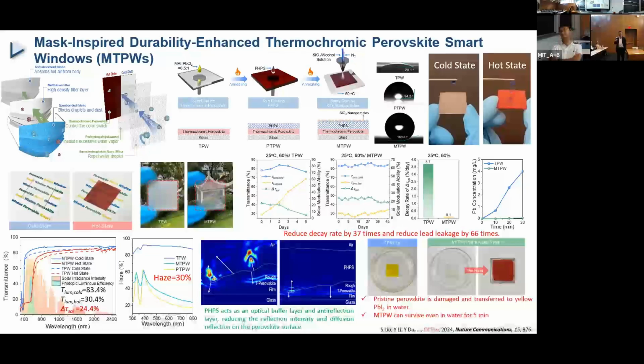This is the previous common perovskite window with a high haze, so that we cannot see the object behind the window. Because the PHPS layer acts as an optical buffer layer and anti-reflection layer, these 2 layers can reduce the reflection intensity and the diffusion. In this way, the haze will be dramatically reduced from 90% to like 30%, so we can see the object clearly. So how about the durability and lifespan?